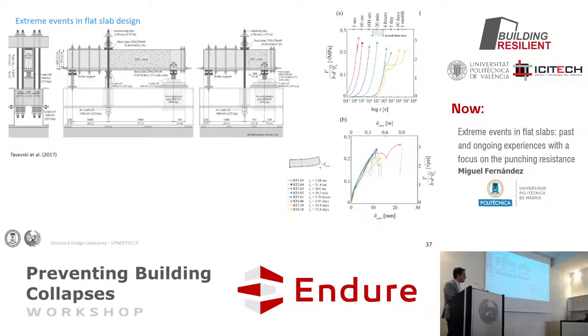There was perhaps a bit of decrease, but even, you may say, yes, but for 1 second it rises. No, it rises, but not necessarily. There was a first failure, and then it dropped, and then we were capable of reloading it. And in fact, the first failure was about the same. And I was going to say, okay, so are the materials changing so dramatically, or what's happening? No, in fact, not at all. That was a very interesting conclusion for me, that the change that may explain why this is a bit higher or there are reductions is not in the material itself.